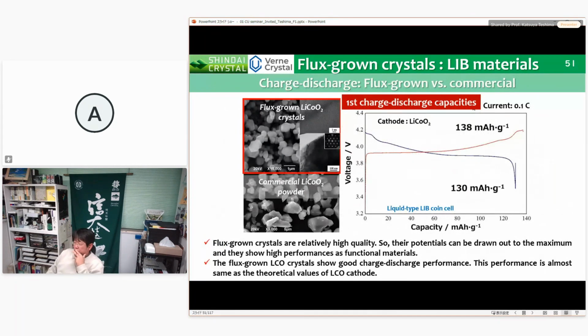This is the charge-discharge performance of the flux-grown LCO crystals. The flux-grown crystals are relatively high quality, so their potentials can be drawn out to the maximum, and they show high performances as functional materials. As a result, the flux-grown crystals show good charge-discharge performances almost the same as the theoretical value of LCO cathode.